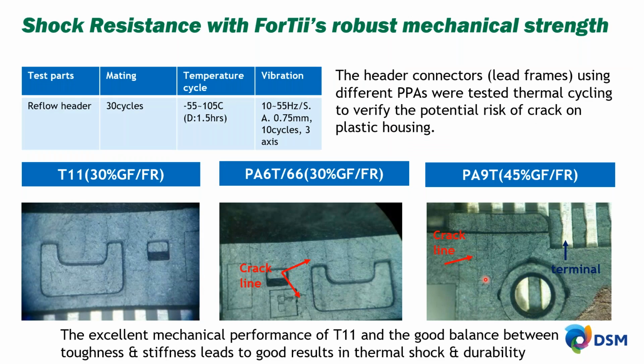Thermal shock resistance is also important in the reflow soldering process, as we mentioned. As the part expands and contracts, you do not want it to exhibit cracking, even along knit lines that form when the part is molded. So these header connectors, you can see, are ForTii T11 material. It's a 30% glass filled and flame retardant version. It does not exhibit cracking even through that thermal cycling. Whereas some of today's PPAs actually do start to have cracks, especially at sharp corners and knit lines, going through the same temperature heating and cooling cycle that you would see in a reflow soldering process. So for minimal thermal shock defects, ForTii T11 can be a good candidate.